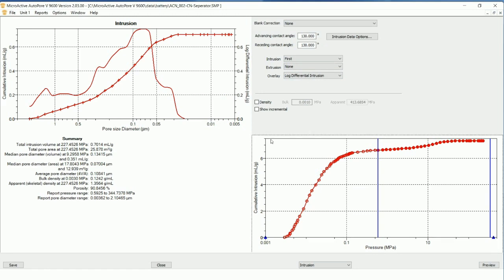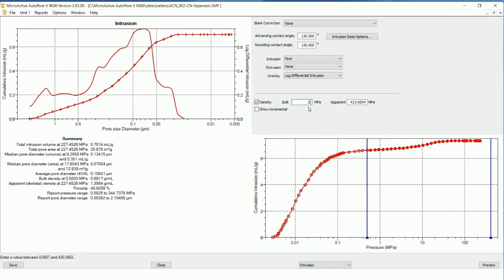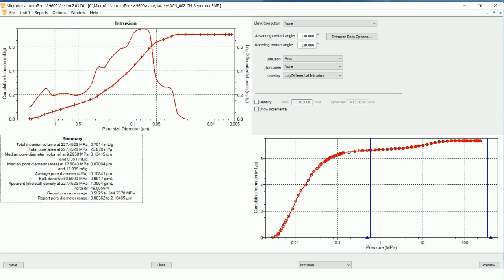And now we do in fact see, if we just change our density value to be calculated, our bulk density to be calculated at the same corresponding value, we see now about 50% for the porosity, and we see here that our median pore size is about 130 nanometers, much closer to what we would expect for a separator plate than what we saw earlier when we included the interstitial filling. So it's just one of the features of the MicroActive.